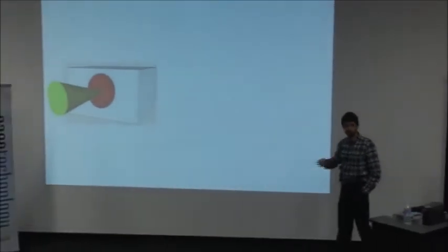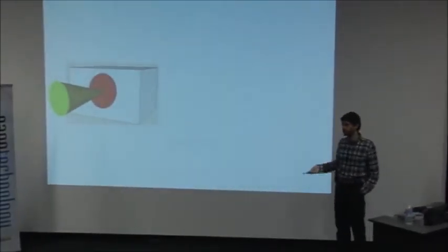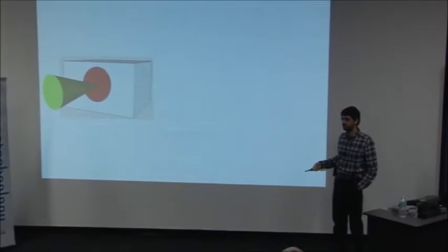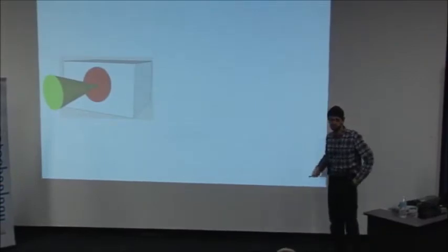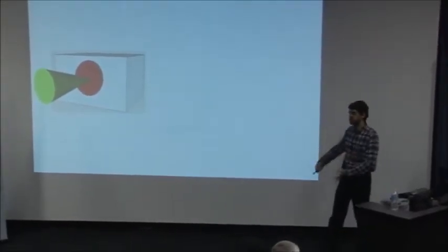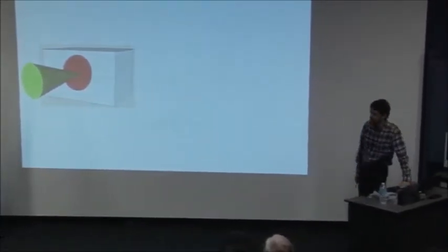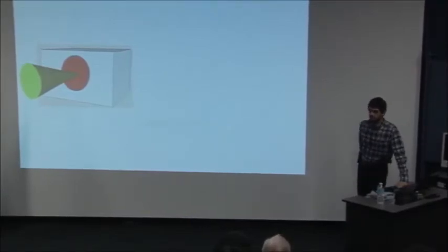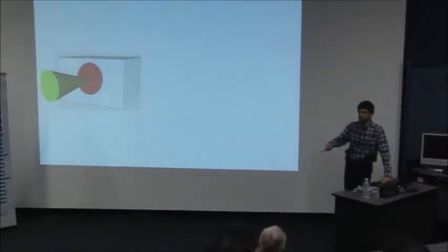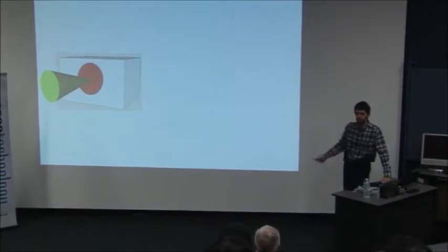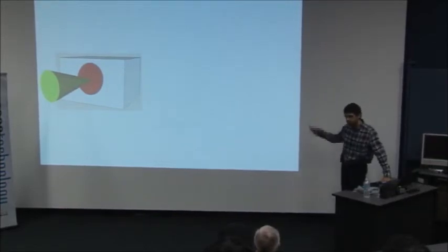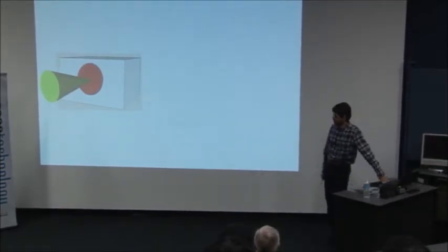You could heat it up really to high temperatures if you pumped in a lot of power. So if you go to, for instance, an accelerator that uses a copper or tungsten electron emitter using the thermionic effect, you will see that it has a big megawatt pulsed laser that can give enough power to heat this up. But we didn't expect any of these because we were just using a continuous wave laser with a few watts or hundreds of milliwatts of power. So just orders of magnitude less than this, right?